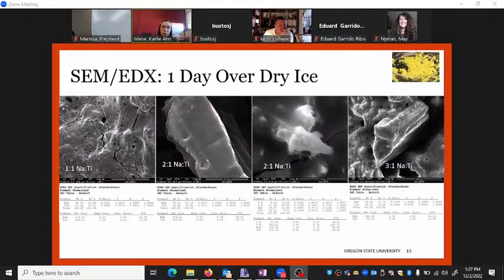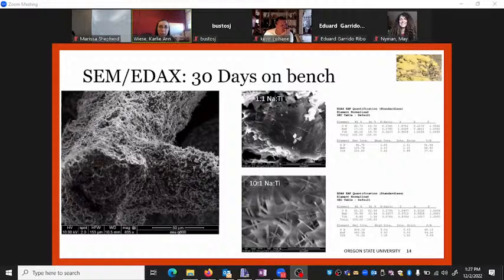Looking at the SEM for my sample after it had been placed over dry ice for a day, you see that it looks totally different. So the structure is obviously changing. It's not the nice pure crystal that we had before. It's losing some of its crystallinity. And the EDX is also showing that the ratios of these different regions are now much different than they were before. And then same with the 30 days on the bench, we see a lot of loss in the crystallinity and change in ratio. So again, something's happening. You know, it's research, it's a process of figuring out what exactly is happening, but we know something's going on.